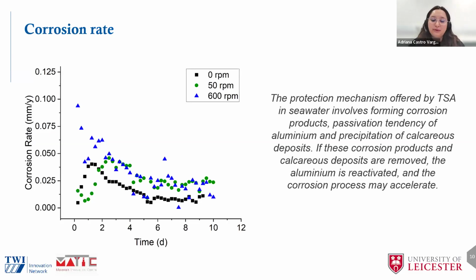So the protection mechanisms offered by TSA in seawater involve forming corrosion products, the passivation tendency of aluminum, and precipitation of calcareous deposit. I will say that the main advantage of these coatings in marine environments is due to the synergy of all these things happening at the same time. However, if these protective layers are removed, then the aluminum is reactivated and the corrosion process might accelerate.